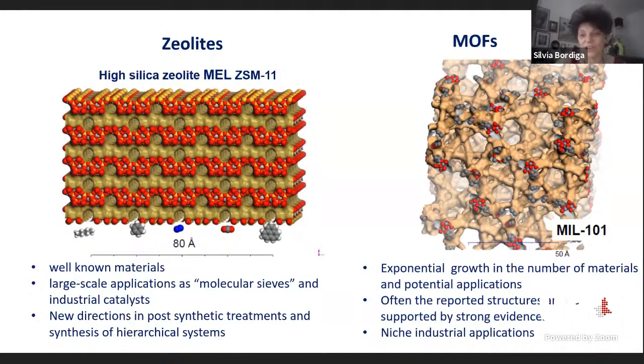Conversely, in respect to metal-organic frameworks, we can say that we have an exponential growth in the number of materials and potential applications. However, at the moment, we have just niche applications of this material for very specific uses, and no big process is performed using this class of material. And we sometimes have some conflict in the interpretation of the results, and sometimes we have a nice drawing of materials with the description of a local site inside these materials, but not always do we have strong evidence about this structure, because we have materials which are extremely complex, and so we should be careful in looking at the literature data in this field.